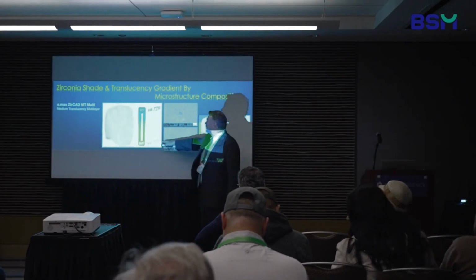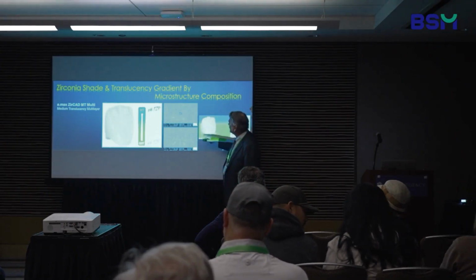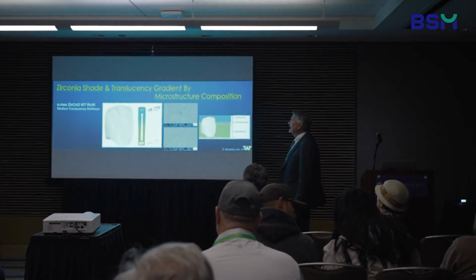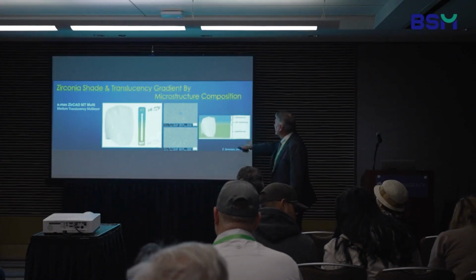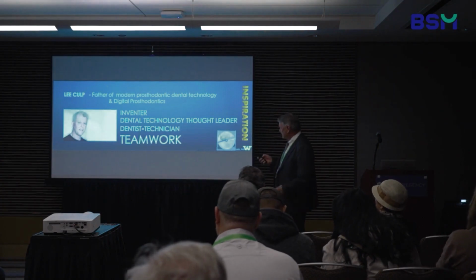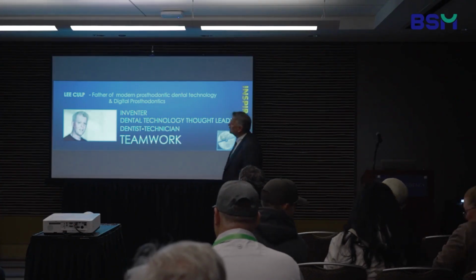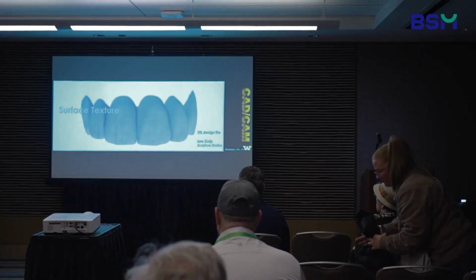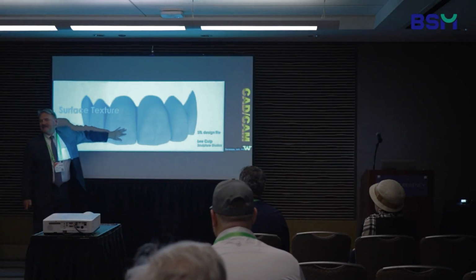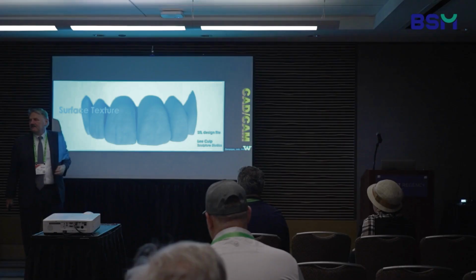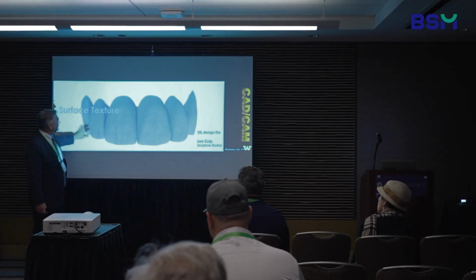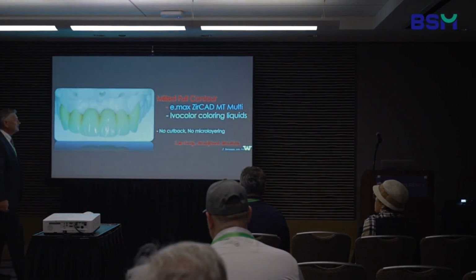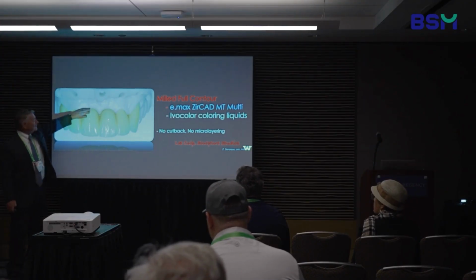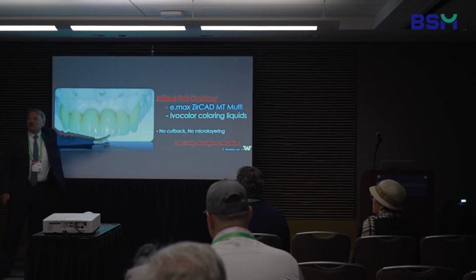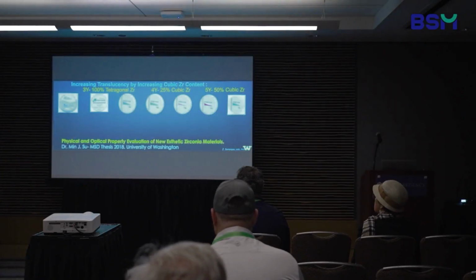They would transition from a 4Y to a 5Y. And now, just by the basic crystalline structure that I have in that disc, and how I want to position or nest my crown in there for how much translucency I want, I can achieve a nicer result. I probably worked the most with Lee Culp for 30-something years. Instead of what Ed teaches, which is to do all this grinding and fooling around with the restoration, what Lee has done is create the surface texture on these teeth, to achieve not only the color from 4Y to 5Y, but a natural surface texture so the light's reflecting similar to the natural teeth.